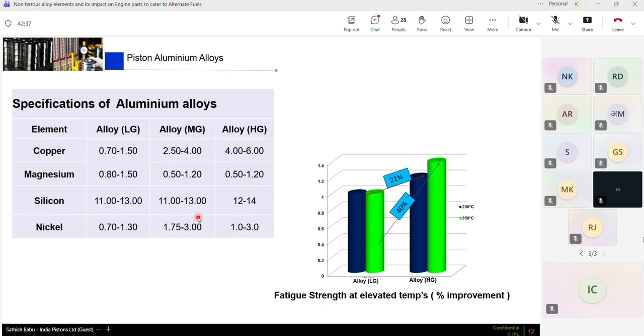And more than that, when these medium grade aluminum alloys started being used in the passenger car, diesel and truck industries, and even the locomotive industries, they started asking for a very high fatigue strength. And we started focusing on the high grade alloys with higher copper content. This helped us make the fatigue strength almost 40% higher compared to the base one at higher temperatures. Because the temperatures inside the byproducts of combustion are typically 1200 to 1500 degrees centigrade, and it will change according to the fuel, gasoline and diesel and other alternate fuels.